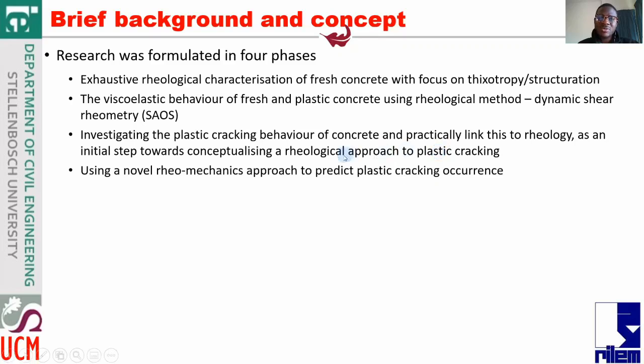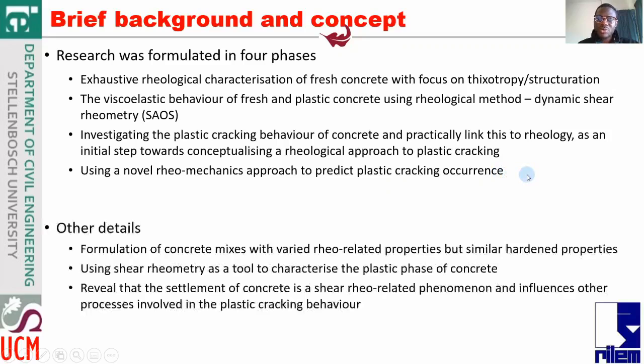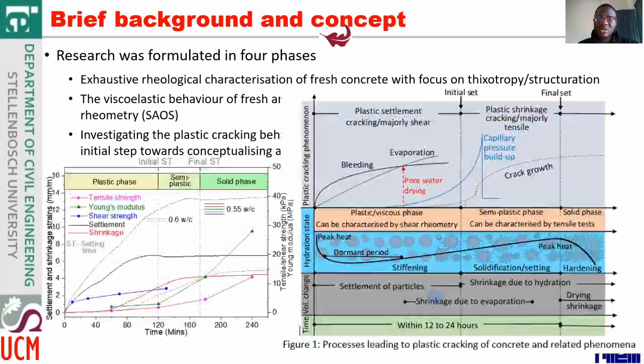And then the final phase of the study was to use a novel rheo-mechanics approach to predict the plastic cracking of concrete. Other details were that we needed to formulate concrete mixes with varied rheology-related properties but similar hardened properties. Shear rheometry was therefore used to characterize the plastic phase of the concrete. We also intended to reveal that the settlement of concrete is a shear-related phenomenon, and it is influenced by and influences other processes involved in plastic cracking behavior.